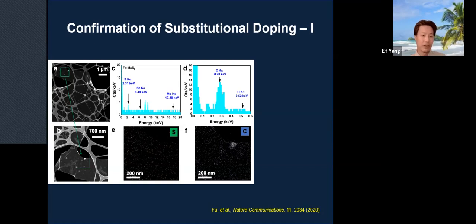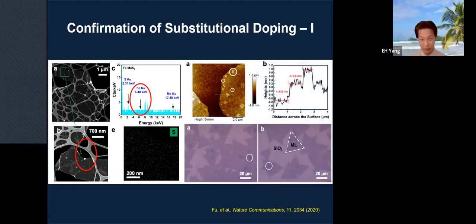So what is shown here in A and B are the low mag TEM image of tungsten. I'm sorry, this is a TEM grid, right? So you have a TEM grid, and we transfer this sample, that iron doped sample, with the PMMA. So naturally you would pick up carbon. So you see this carbon residue in figure B, and that is picked up in C and also D, right? But in the center top, that's C, you don't see any iron elements here. This is because this EDS spectra is not sensitive enough to pick up the signal from the substituted atoms. So you are not supposed to see it. If you see it, then you may see some residues and some adsorbed material somewhere, right? So this is good. Now we double confirm that using AFM, and on the right top and the right bottom shows the optical images. As you can see, the samples are clean, right?